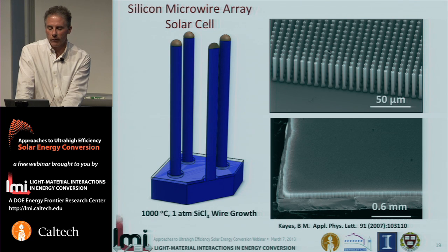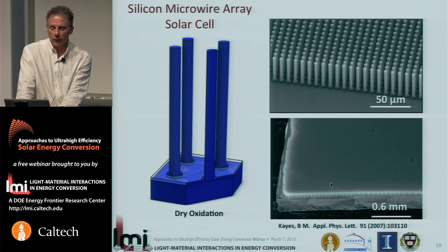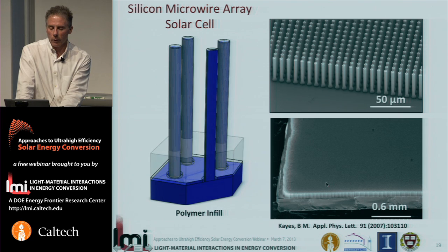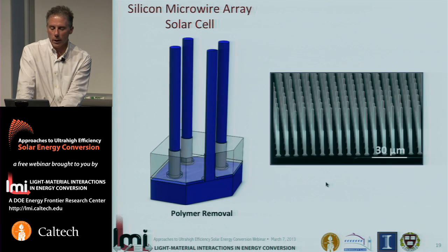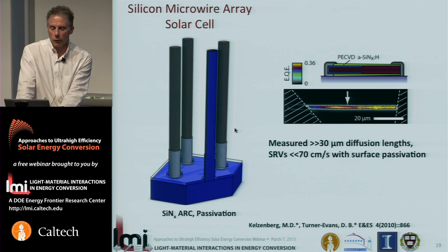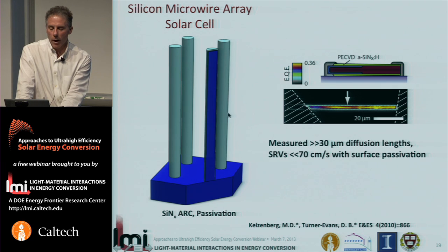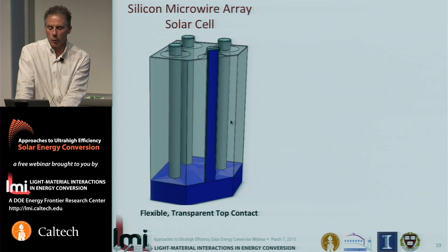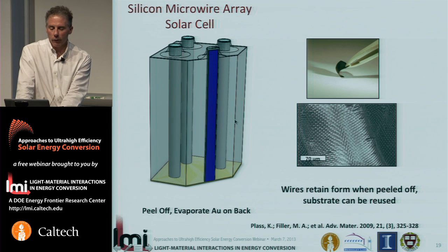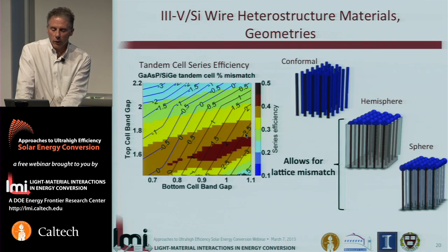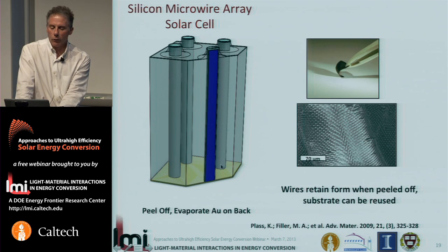Large uniform arrays of wires can be fabricated over typical areas that are comparable to typical photovoltaic cells, and by a series of processing steps that mirrors the processing steps that are used in conventional photovoltaic cells for silicon fabrication, it's possible to make diffused PN junctions, coat them with anti-reflection and passivation layers that give rise to efficient photocarrier collection, and then finally to encapsulate the whole structure in a polymer with a transparent metal front contact, such that the cell is peeled off the substrate, making a flexible thin film cell. So this is an approach for making an extremely efficient light trapping structure that is also at the same time a waferless thin film silicon cell.